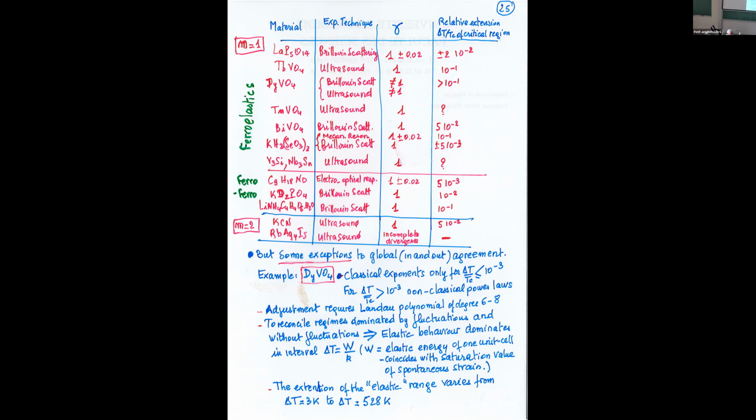For example, if you go from tetragonal to orthorhombic, then it's clear that both of them have 90-degree angles, so here you don't need a shear strain. But if you go from orthorhombic to monoclinic, then you will need a shear strain because one of the planes will be deformed. But you have to see, of course, the n equal 1 and n equal 2 also in the reciprocal space, because fluctuations are in the reciprocal space. And so this is the difference.